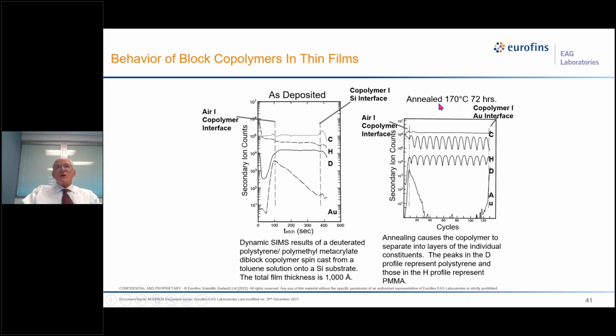And after annealing them at 170 degrees for a few days, you can see that this causes the block copolymer to separate into individual layers. And the deuterium peaks represent the profile of the polystyrene, and the hydrogen represents the profile of the PMMA. So pretty slick. And we did a lot more analyses like this years ago. So isotope analysis, polymers, insulators. I won't say no problem, but it certainly can be done with a little practice.